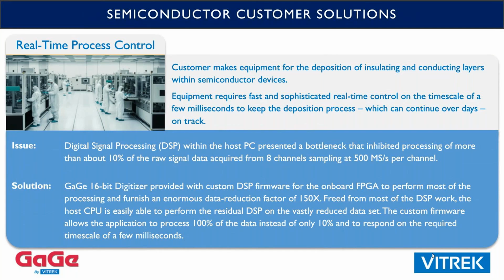So in this example, the firmware that we developed for the customer picks out things like amplitudes and zero crossing positions of the waveform. And you can see how if you have thousands of points and reduce that to a single amplitude, you can get huge reduction factors. And indeed, we were able to achieve a reduction factor from this data that's coming in on 8 channels at 500 megasamples per second. We achieved a data reduction factor of about 150.